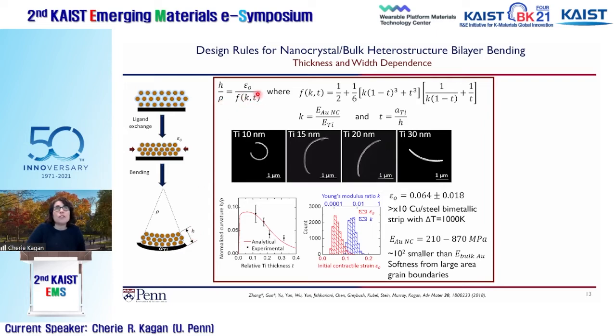And the rest of this function only looks very busy, but it only has two sets of parameters. One is K, which is the ratio of the Young's modulus, which is a measure of its mechanical properties, of the nanocrystal film, something that we didn't know, in comparison to that of bulk titanium, which we do know, right? You can look that up in a table, it's a materials property. And then the T is the ratio of the thicknesses, which we could measure.